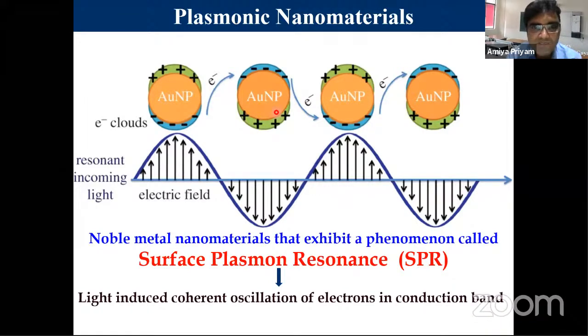The characteristic frequency varies from metal to metal. For example, spherical gold typically absorbs around 500 nanometers, whereas a typical silver nanoparticle will absorb around 400 nanometers. This surface plasmon resonance can be put to use in various applications, like catalysis, like sensing, and also in therapy.